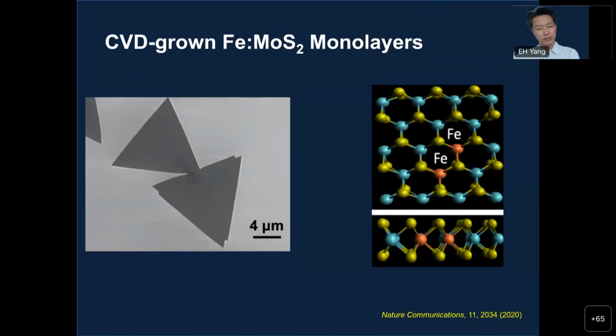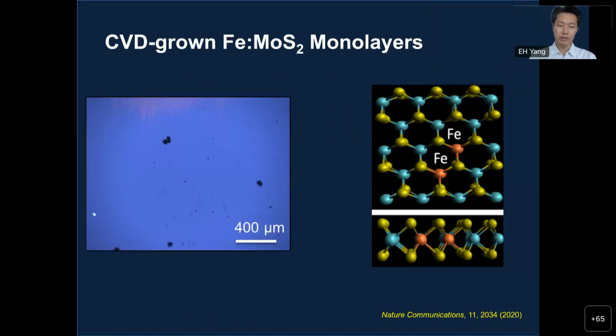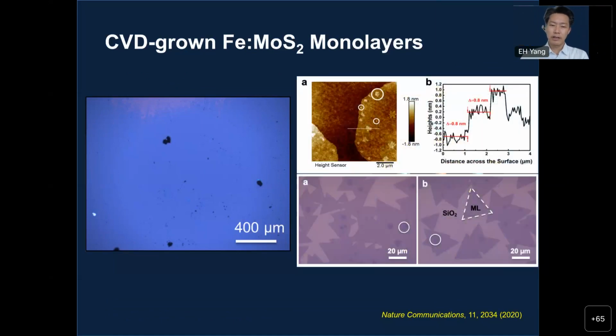So that's the result. Typically, you can get single crystals of iron doped molybdenum sulfide monolayers, or by tweaking the growth conditions, one can get continuous large, millimeter scale monolayers. And we examined this AFM scan here to get the thickness. Basically 0.8 nanometer is the typical thickness you get from a monolayer molybdenum sulfide, and optical images also show very clean iron doped triangles here with some sporadic bilayers there.